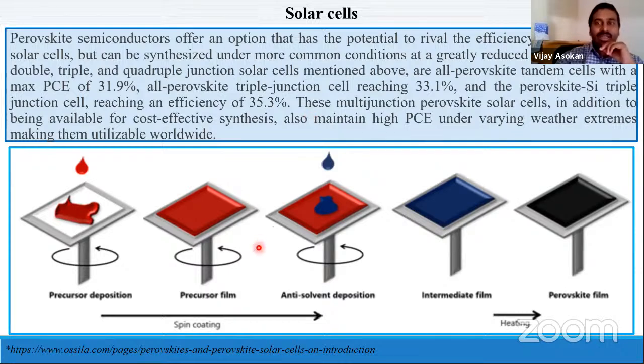And most of the perovskite devices can be constructed by using the precursor deposition, making a film, then anti-solvent deposition and making an intermediate film, then making the total perovskite film by heating. So there is a possibility for using spin coating or spray pyrolysis, and mostly it can be constructed in a laboratory. But when we are considering perovskite solar cell device construction, the key point is a vacuum environment in order to avoid the reaction of oxygen, which causes deterioration of the perovskite structures.